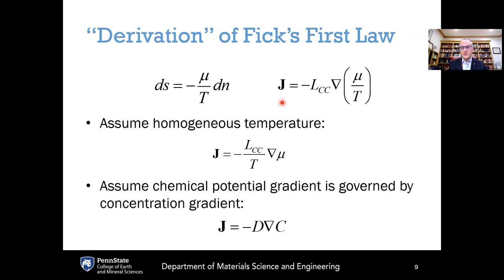And therefore, the relevant flux equation, where we consider only one thermodynamic property, which is just our concentration, only has one term in that case. So the flux of matter here, J, is equal to minus the kinetic coefficient, which I've listed here as LCC, meaning it is from the affinity of the concentration acting on changes in the concentration profile. This will be related to the diffusion coefficient in a moment. So minus our kinetic coefficient, LCC, times the gradient of the chemical potential divided by the temperature here, so mu over T.